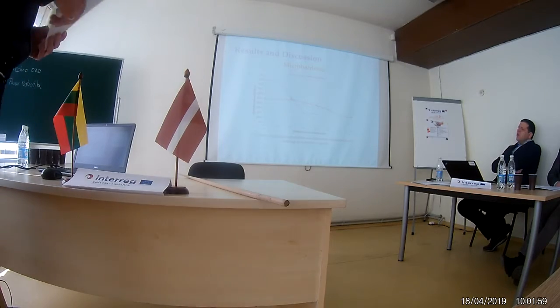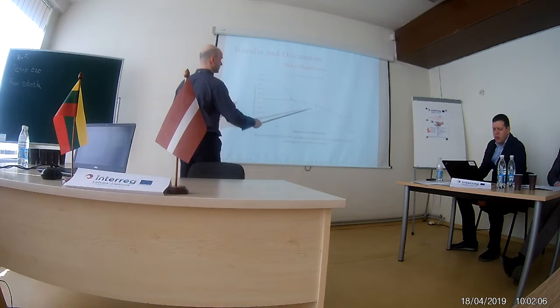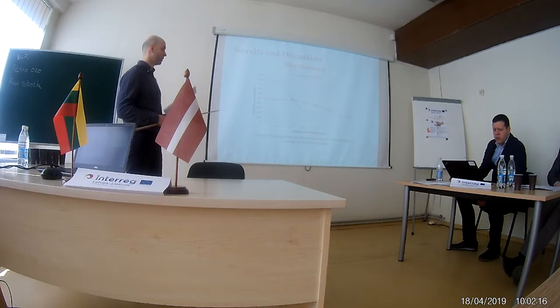By comparing both through-depth distribution profiles of microhardness between produced coatings, it is seen that a smooth transition of properties for the second group coatings was obtained. Considering that hardness correlates to the strength of the material, a similar gradient can be inherent to the internal stress distribution inside the coatings.